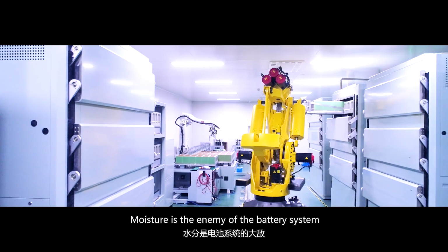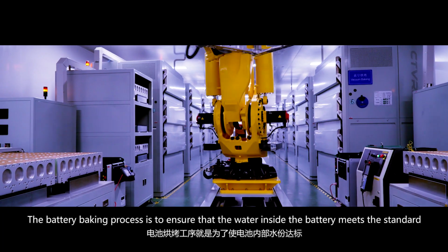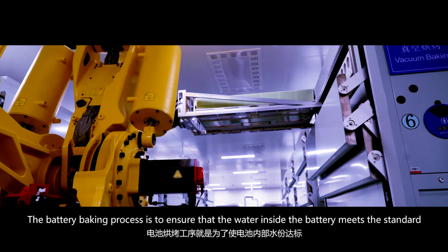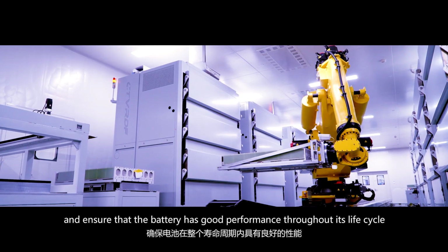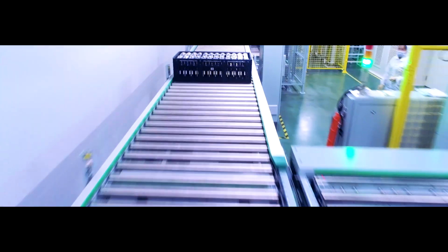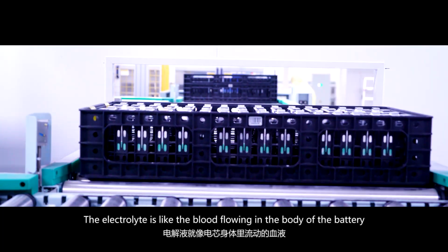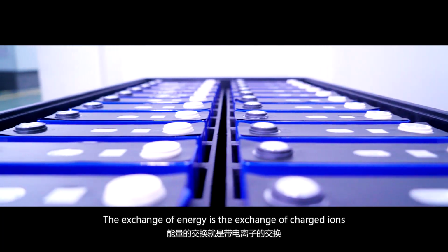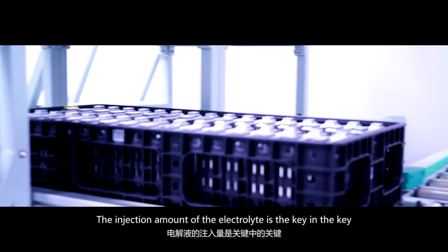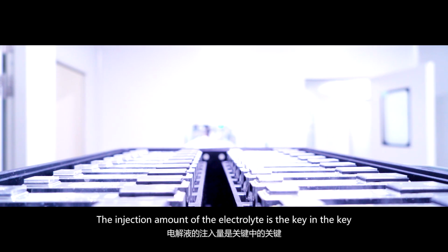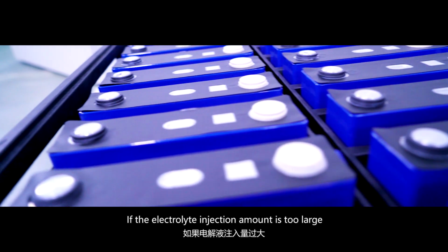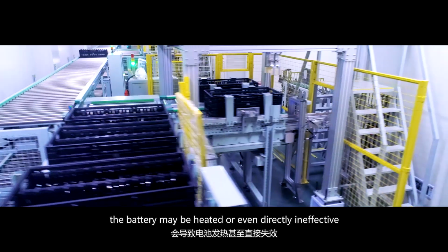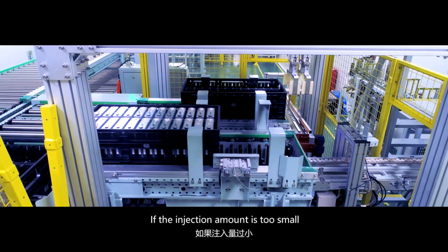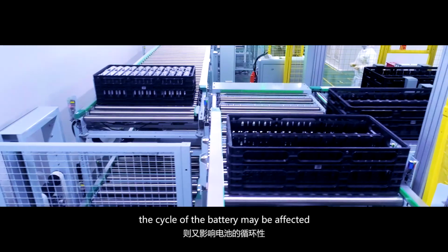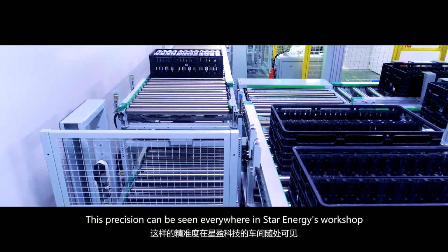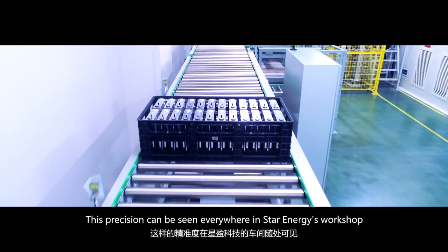Moisture is the enemy of the battery system. The battery baking process is to ensure that the water inside the battery meets the standard and ensure that the battery has good performance throughout its life cycle. The electrolyte is like the blood flowing in the body of the battery. The exchange of energy is the exchange of charged ions. The injection amount of the electrolyte is the key in the key. If the electrolyte injection amount is too large, the battery may be heated or even directly fail. If the injection amount is too small, the cycle of the battery may be affected. This precision can be seen everywhere in Star Energy's workshop.